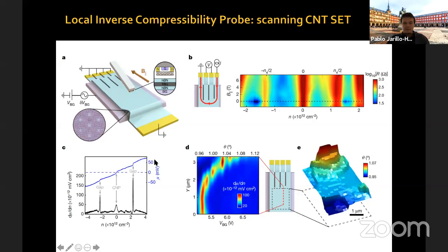If you integrate the dμ/dn, you can actually look at the chemical potential as a function of density. And then again, we can do this mapping locally. If you look at a given feature, for example one of these peaks, which tells us the angle for this magic angle graphene device, because this band insulator peak tells you what the angle is, you can see that as a function of location, we can find that this angle is changing locally. Because this is a device which has a certain area and there are local variations in the twist angle.